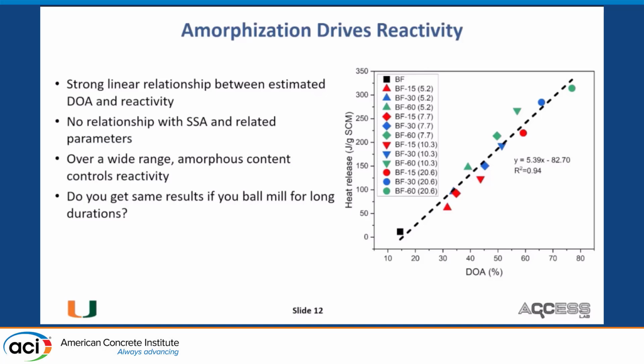So when we plot, on the other hand, the degree of amorphization and the heat release, we actually see a really nice, strong linear correlation that suggests that the heat release basically depends on the degree of amorphization, and you have this nice relationship. We tried to include SSA in this. We tried to plot separately with SSA. Absolutely no relationship was seen.